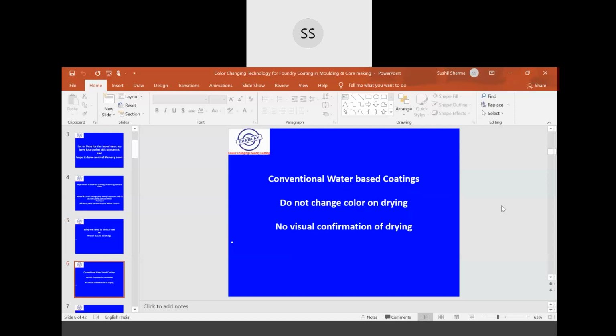Now, conventional water-based coatings, as we all know, are white in color. If they are zircon-based coatings or aluminosilicate coatings, they are in certain colors from different suppliers. The biggest challenge in front of the foundryman when these water-based coatings are used is how to ensure that the coatings are drying, that the total moisture is removed from the coating. Because whenever you are using aluminosilicate-based coatings, particularly for automobile castings, the water concentration in the coating is on average almost 50%.